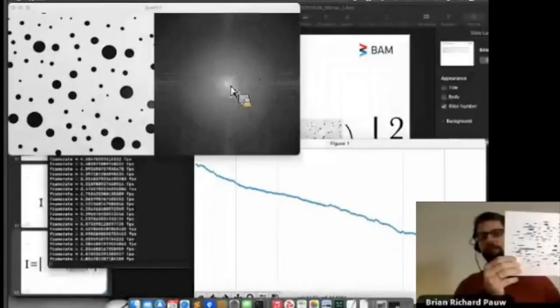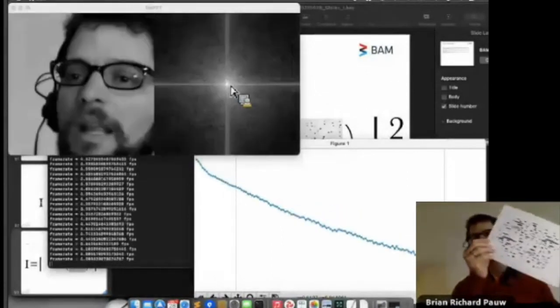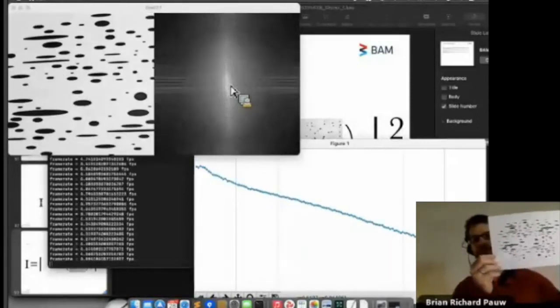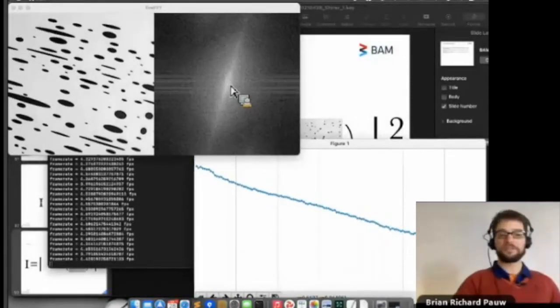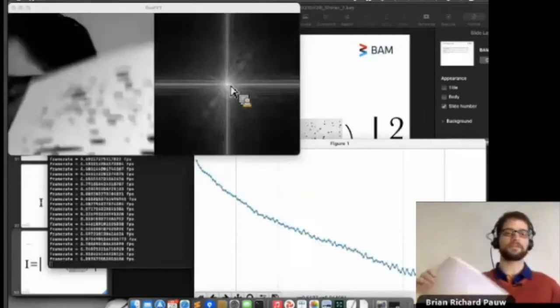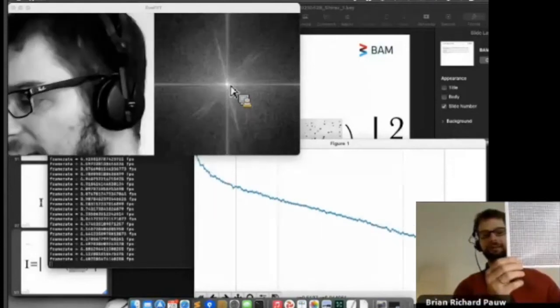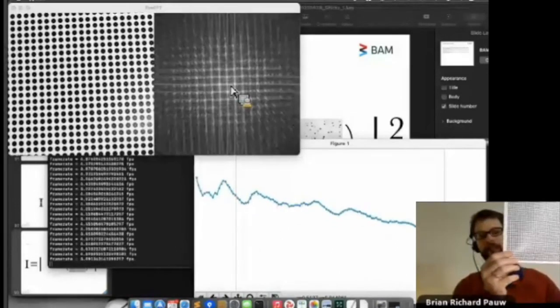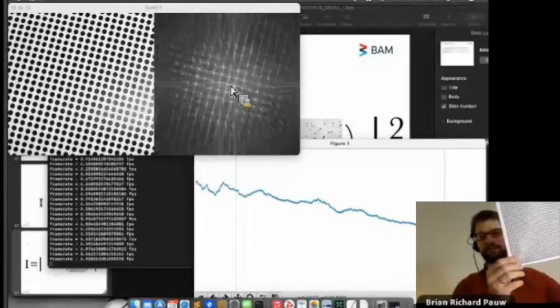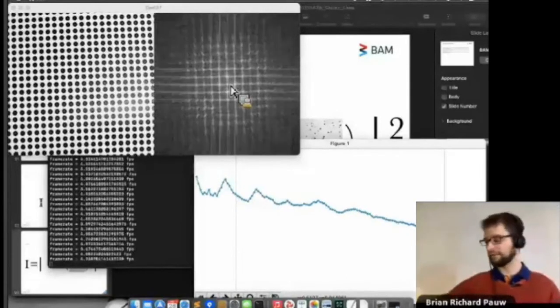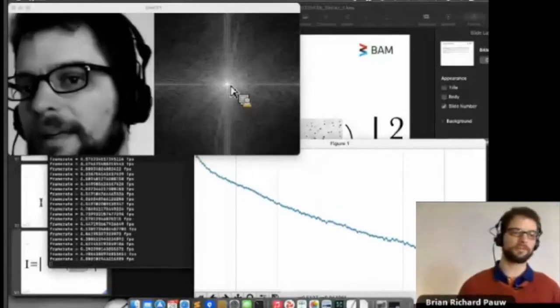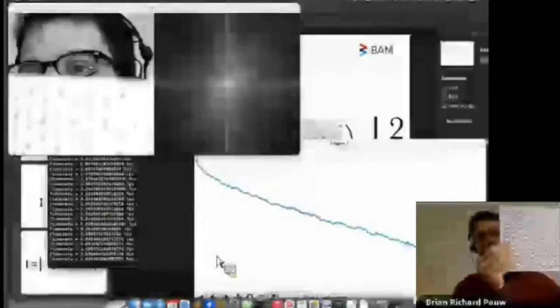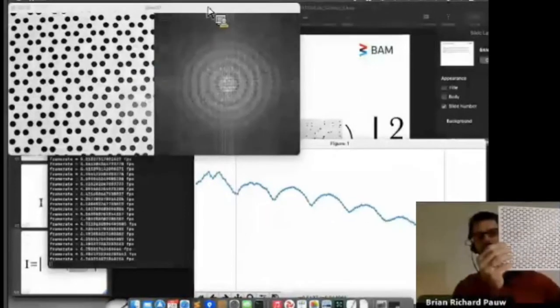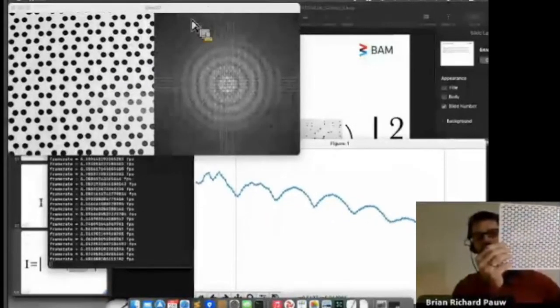For oriented polydispersed systems, you still get this orientation, still this anisotropy in your scattering pattern, but again, the oscillations are pretty much gone. Now, since I'm here, let me explain also X-ray diffraction. X-ray diffraction is the same thing, but with a regular lattice over there. So you still have the form factor as we saw before, but now you have this form factor convoluted with a lattice. And the lattice comes from the regular spacing in your system. And it doesn't just work for square lattices, it also works for hexagonal lattices. And here you can very clearly see the Fourier transform of the object itself, of the spheres, and the lattice from this hexagonal structure.